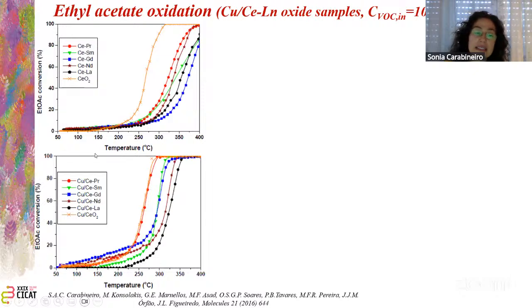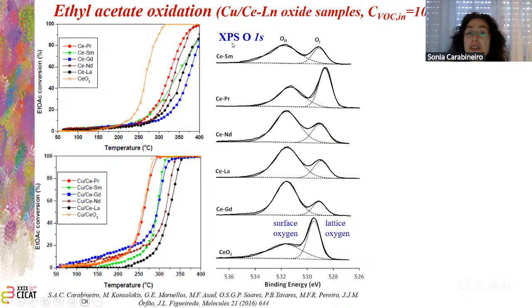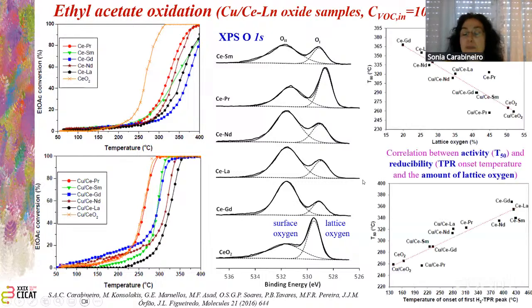copper on these cerium lanthanide oxide samples, okay, different ones with samarium, gadolinium, neodymium, and so on. So we checked the XPS oxygen 1s peaks. So here, the peak at lower binding energy is the lattice oxygen peak, and at higher binding energy, the surface oxygen peak. So we obtain a correlation between catalytic activity and reducibility, okay?